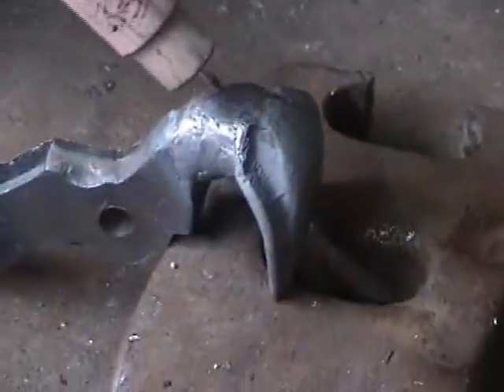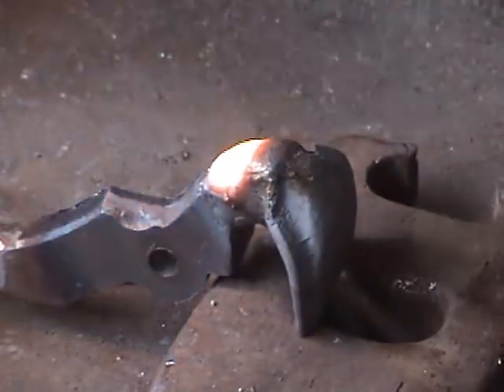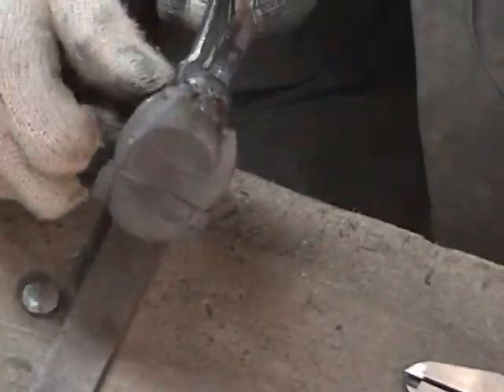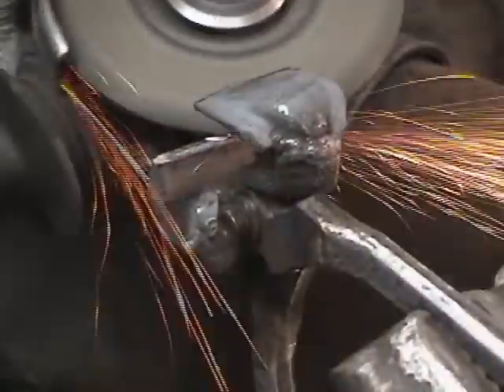We use a TIG welder to weld the blade on. The guy doing the welding should be pretty handy because it takes superb penetration to be sure that the blade will never break off.